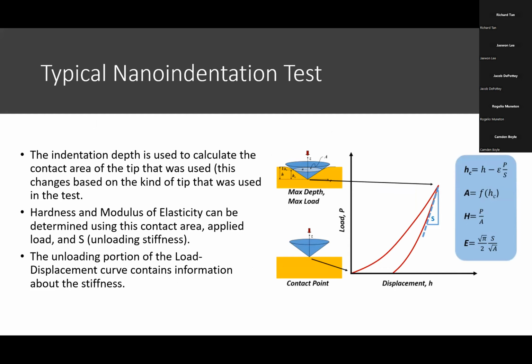So here we have the indentation depth when the tip has an applied load to the surface of the material. You can use that depth to calculate the contact area that the tip has left, and based on that area depends on the tip that you use. So the hardness and modulus of elasticity, or Young's modulus, can be determined using this contact area, the applied load, and the unloading stiffness.